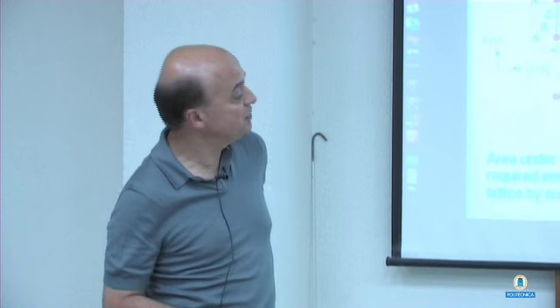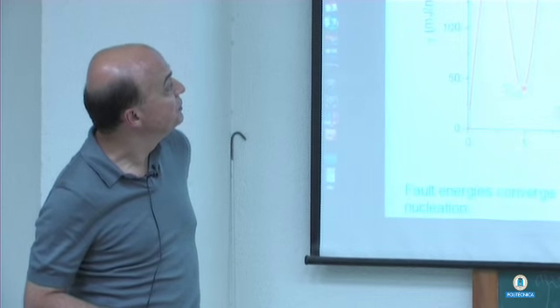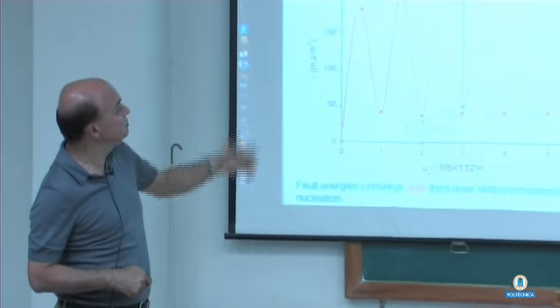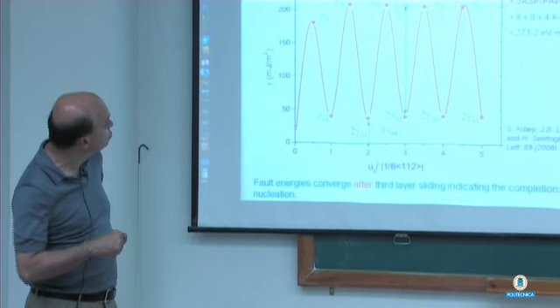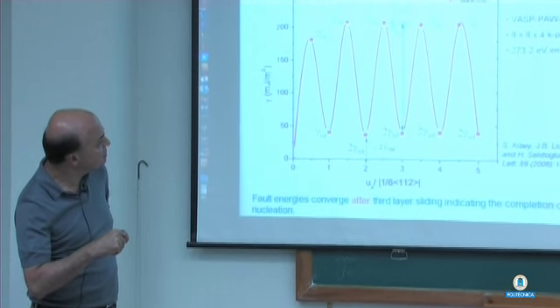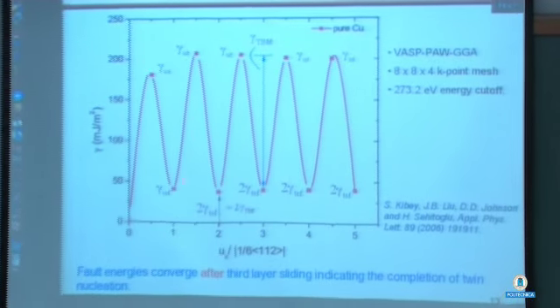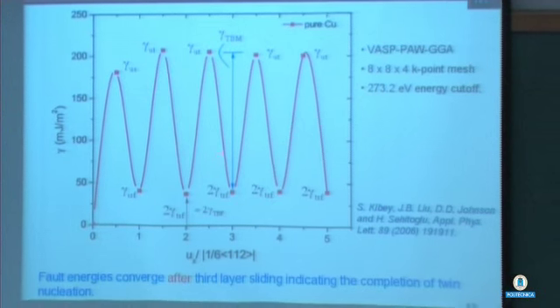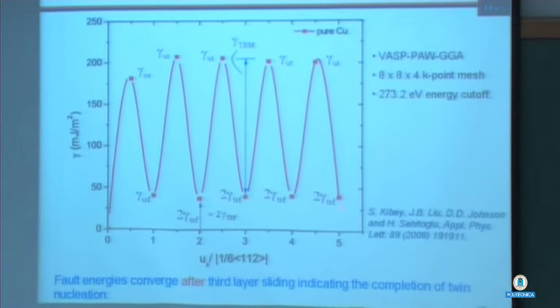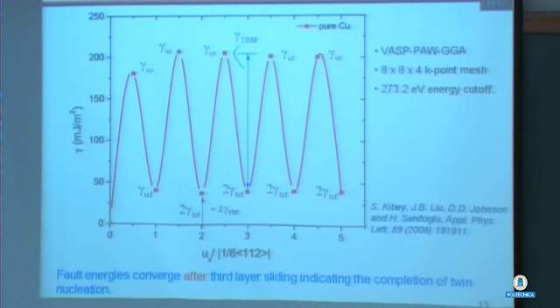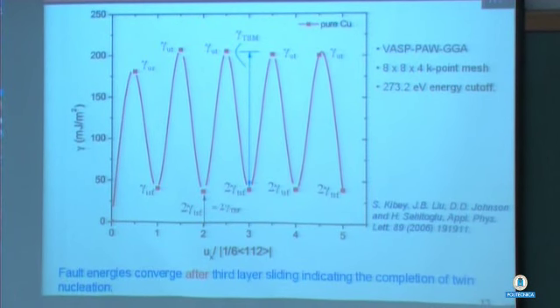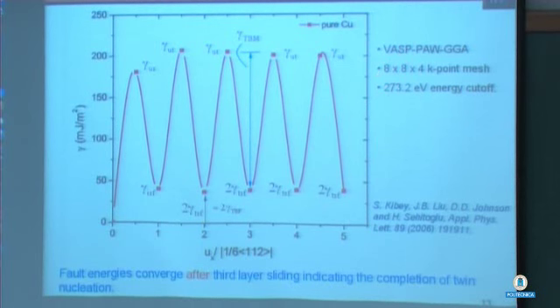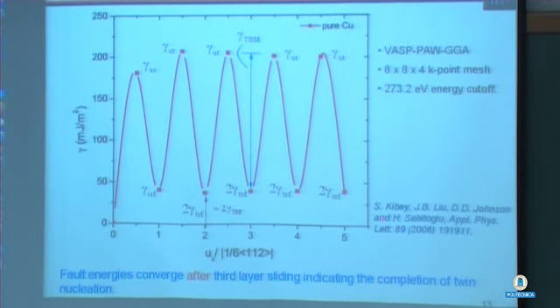Now, the area under this curve is the required energy to twin the lattice by successive shear. Looking at this for copper, for example, you can see gamma US is here, gamma UT is different, the numbers are different, okay? But after a few layers, things stabilize reasonably well. So this is for pure copper. These calculations are density functional theory calculations. This is published in APL. Fault energies converge after the third layer.